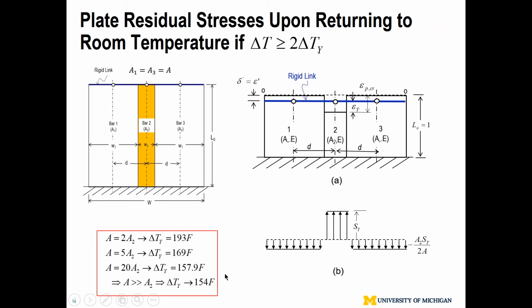So again, that's the message. Then the question is, how does this relate to practice? I'm using a fully restrained 1-bar model. If I consider a big plate and heat up a middle area, making it symmetric, then we can solve a 3-bar model. Without getting into the detail, you just have to trust me. The question is, what does it take for delta Ty to be reached, what will be the delta Ty, and how can that be compared with the fully restrained condition.